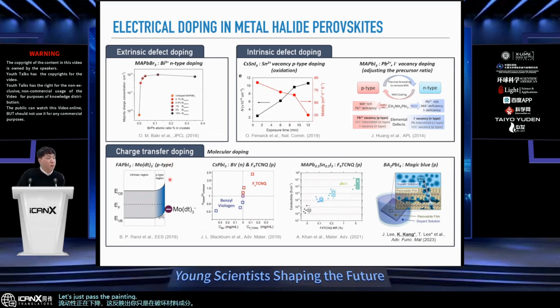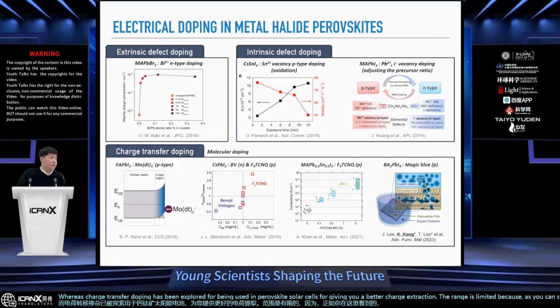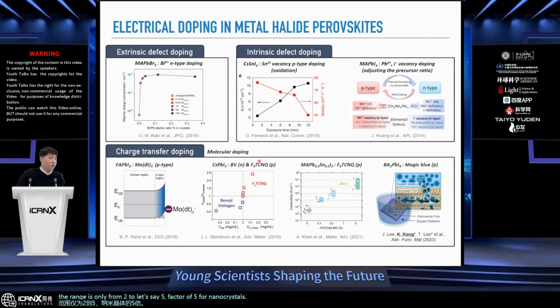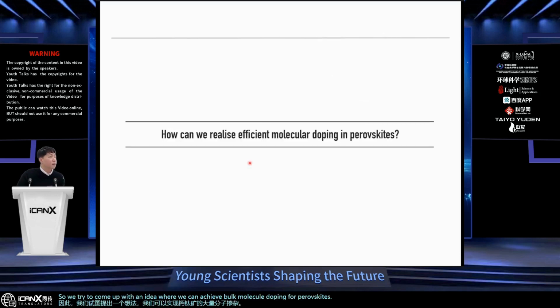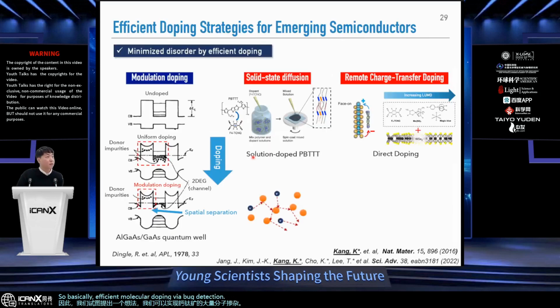Whereas charge transfer doping has been explored in perovskite solar cells for giving you better charge extraction. The range is limited because, as you can see here, the range is only from 2 to, let's say, a factor of 5 for nanocrystals. And we thought this was because this is only playing at the interface. So we tried to come up with an idea where we can achieve bulk molecular doping for perovskites. So basically, efficient molecular doping via bulk doping in perovskites.